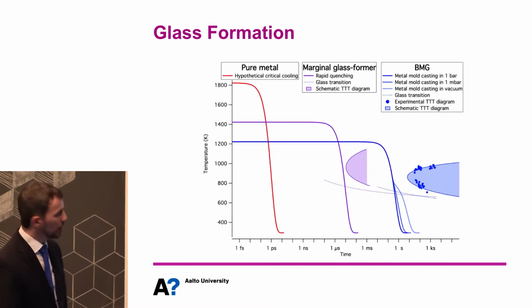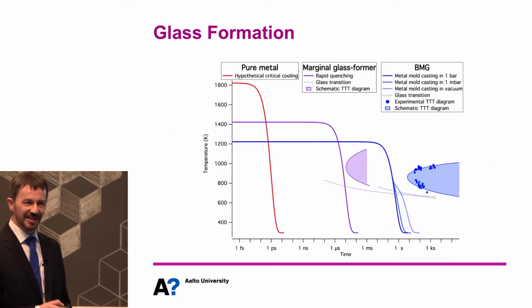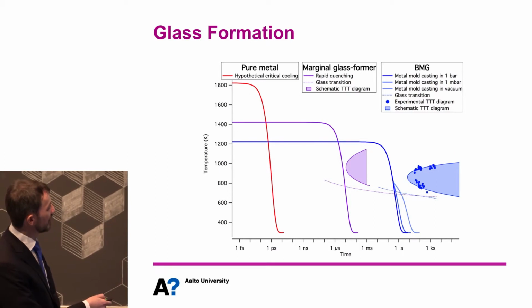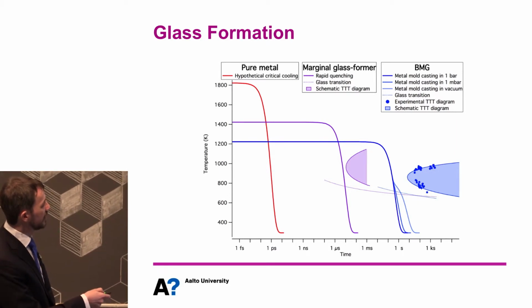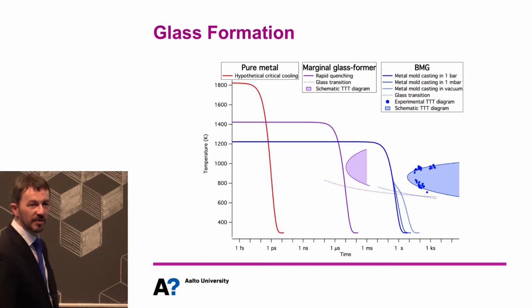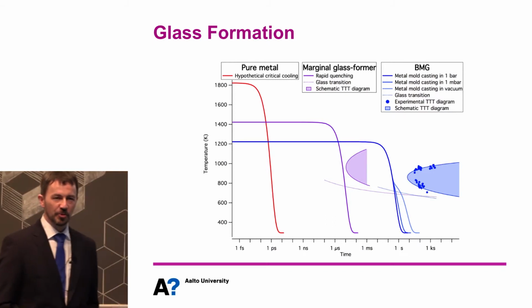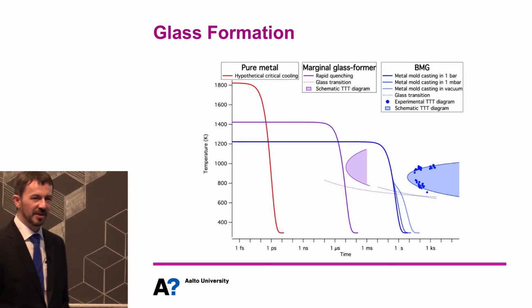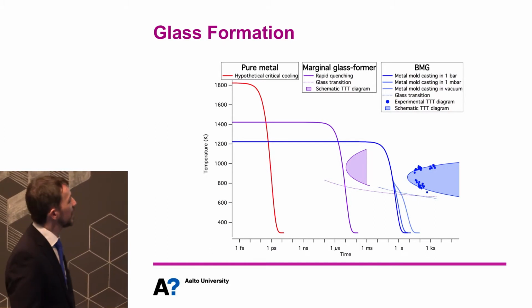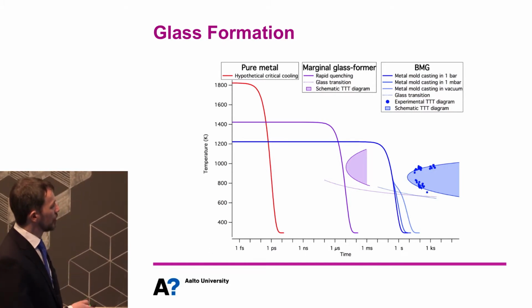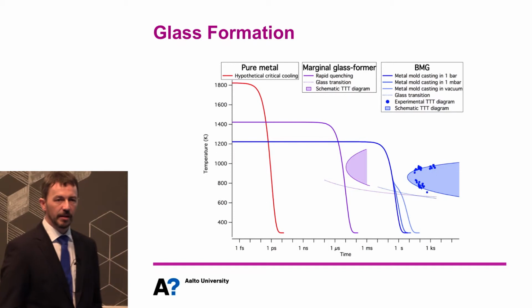But with glass-forming alloys, you can actually measure this experimentally. This one all the way out here on the right, these dots here show data points where people have measured how long it takes a liquid to crystallize. And those alloys have only been around for something like 20 years.